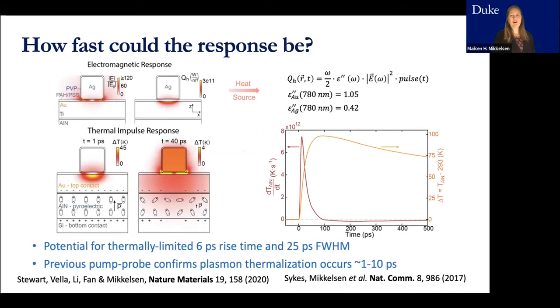So we started to think about how fast the response could be. We did simulations with Xianghui Fan at Stanford as well. And we could see from these very simplified simulations at the moment that they're showing very fast response times. So we have the electric field here that we can put into looking at the heat that's generated and the temperature change here at 1 picosecond and at 40 picoseconds.